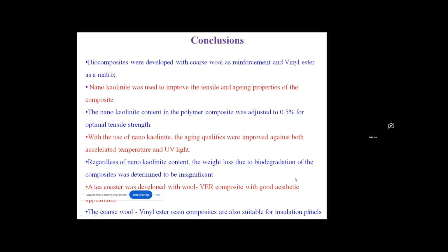So coming to the conclusion, we made biocomposites from coarse wool and vinyl ester resin. Inside that, we added nano kaolinite as a filler to enhance the mechanical properties. Out of 3 combinations of nano kaolinite we added, the 0.5% is showing the best result in terms of tensile strength. And aging qualities related to accelerated temperature and UV aging were found to be higher with the addition of nano kaolinite in comparison with the neat composite. Now the weight loss doesn't show any difference irrespective of the addition of nano kaolinite.